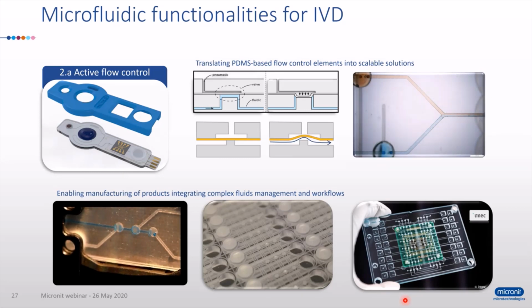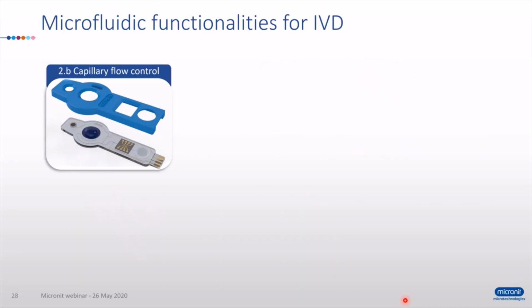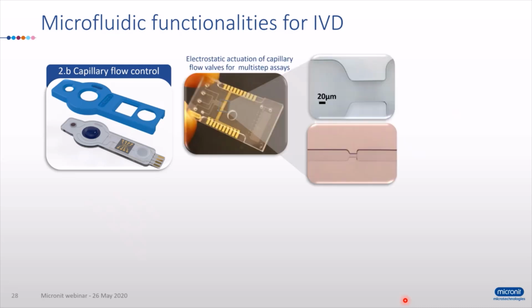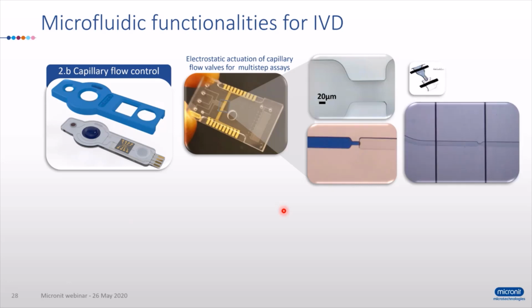The second type of flow control I want to mention is capillary flow control. In capillary flow control, flow is basically determined by the geometry of the channels and by the surface properties in the channels. So like in this case, you see the blue fluid flows spontaneously inside the channel up to this geometrical restriction and then expansion, which constitutes the valve, basically. These valves, these flow control elements can be fabricated, for example, by hot embossing in polymer, or when scaling up by injection molding.